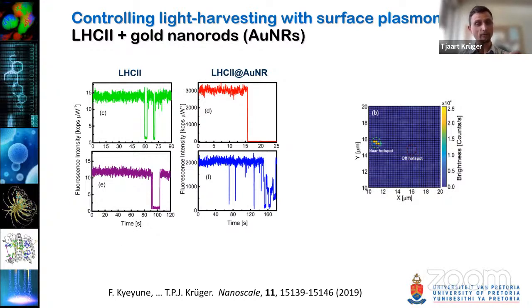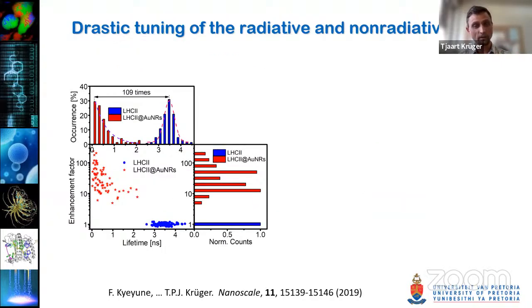Okay, so this means that the radiative rate is significantly affected by the presence of the plasmon field. But the non-radiative rate is also significantly affected. So here is the fluorescence enhancement factor, and the lifetime. The non-radiative rate changes the lifetime. So the higher the non-radiative rate is, the shorter the lifetime is. So here are some LHC2 that are far away from a hotspot, and when they are coupled to the plasmon fields or inside a hotspot, you get a significant enhancement in the fluorescence and a concomitant decrease in the lifetime.